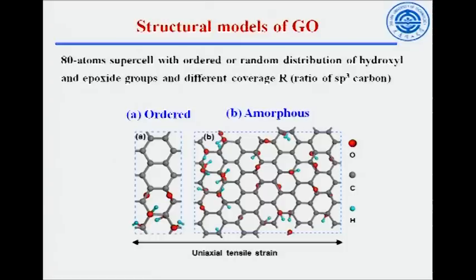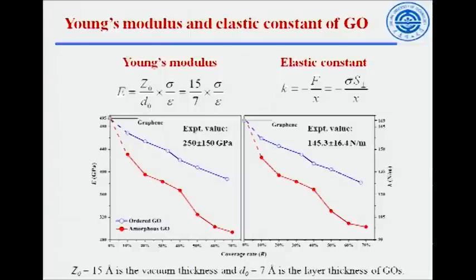Then we use these ordered or amorphous structural models to study the mechanical property of graphene oxide. We put either ordered or random distributions of hydroxyl and epoxide groups on the graphene, and then we study the effect of coverage, or we can say oxidation rate. What we find is that the Young's modulus drops, but rather slowly, with increasing oxidation rate. The number we get here agrees very well with experimental measurement, about 250 or something around. That's the Young's modulus, and we can also reproduce the elastic constant, which is also reduced from pristine graphene. As you increase the oxidation rate, it drops slowly.